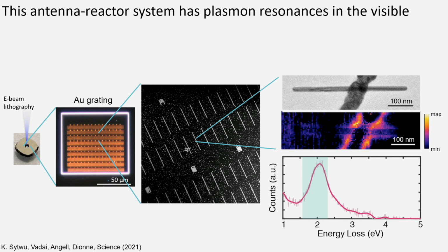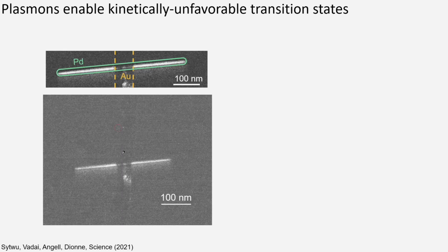You can see that this particular system has basically the predicted near field enhancement over the junction between the gold bar and the palladium nanorod. And basically it absorbs light most strongly at visible frequencies in the red, so right around 600 or so nanometers.